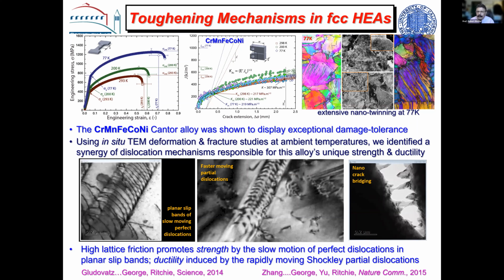it gets more ductile. If you look at the structure, it's the simplest structure you could ever see. It's basically a single phase equiax grain size. There's no fancy microstructure in there. There's no precipitates that you can really speak of. But what you do find is that when you go to low temperatures, you get twinning, get nice twinning. But these were a new class of alloys because they were concentrated solid solutions. They tended to have sluggish diffusion. They tend to have a little bit more lattice friction to dislocation motion because there's different elements.